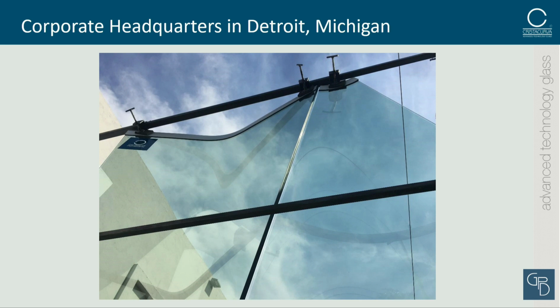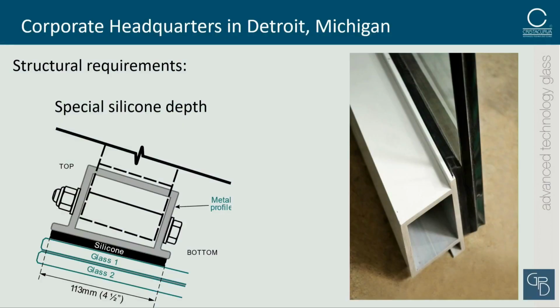And so we moved on to the next step, which was how we were going to go about the installation of the glass. Again, in close collaboration with the glazing contractor, we determined the best way to approach this. First I've got to rewind a little bit. The glass had to be annealed because of the shape, so there was no way that we could drill the glass to a facade. So engineers determined that the glass had to be glazed with a 4 1/2-inch or 113 millimeters depth silicone bite. And that's a very special silicone bite.